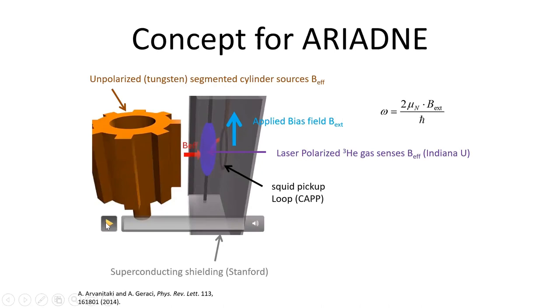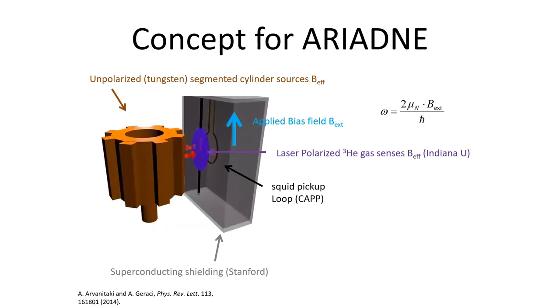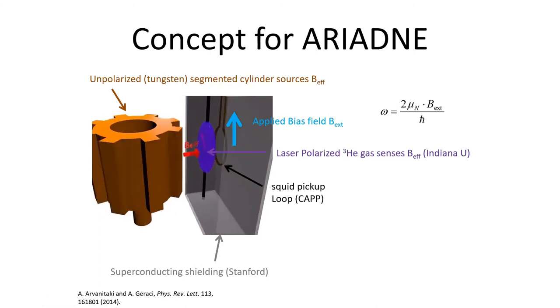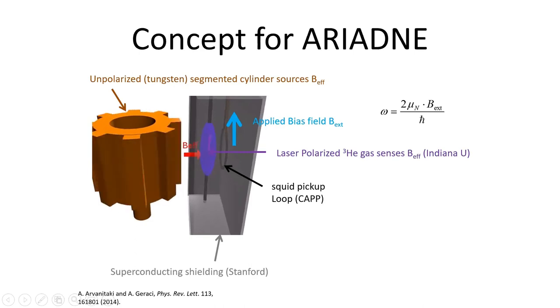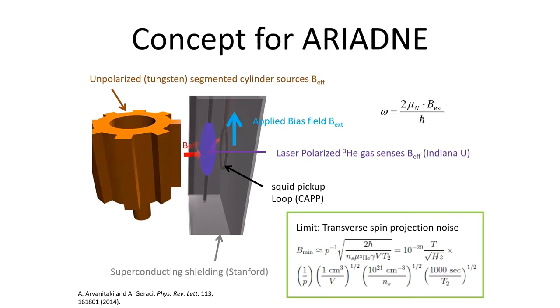And so we arrange the situation so that the teeth are passing by at the nuclear Larmor precession frequency so that we're resonantly driving the spin precession, which can then be picked up using a pickup loop with a SQUID magnetometer that's being developed by our collaborators here at CAPP and at KRISS in Korea. So the fundamental limit of sensitivity of this experiment is going to be given by the transverse quantum spin projection noise. And so this scales like 1 over the square root of the product of the volume, the density, and this T2 time, this transverse decoherence time. And so to get better sensitivity, we want high density, we want high T2 time, and as large a sample volume as possible for the interaction length scale that we're looking at.